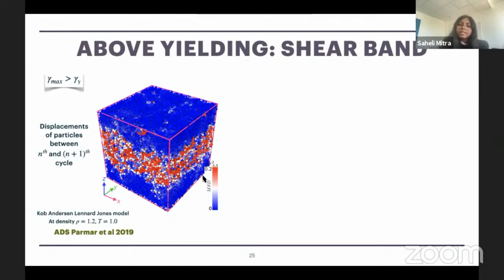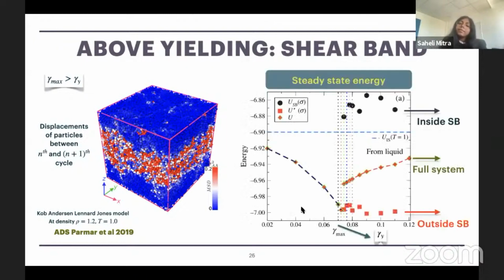So if we plot the steady state energies, what we see is below yielding, the energy of the system decreases because of annealing, and above yielding, the energy jumps to a higher value. But a more close examination will reveal that inside the shear band, actually the energy is higher compared to the part outside of the shear band. This gives us an indication that the structure in different parts of the system in the presence of a shear band might have a different nature. We'll come back to this point when we'll be discussing hyperuniformity and local structural order.